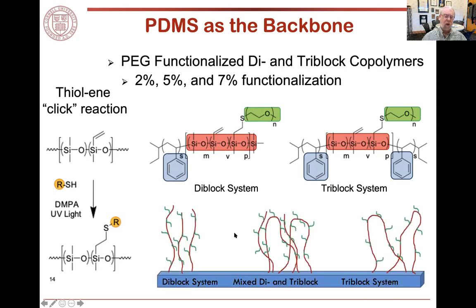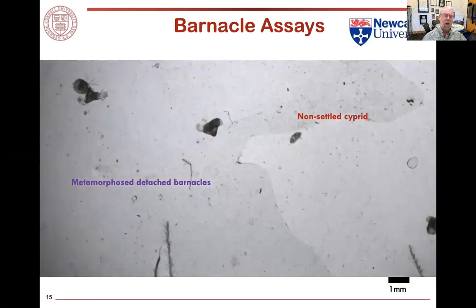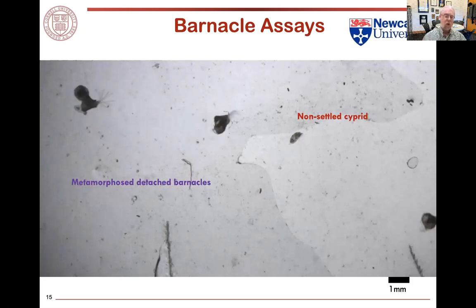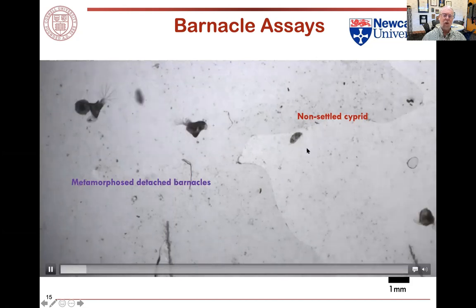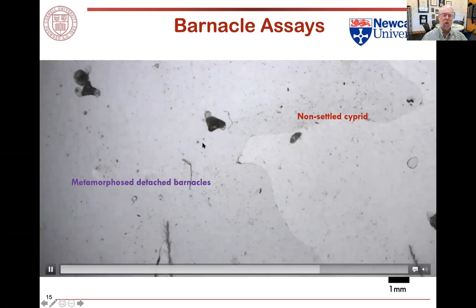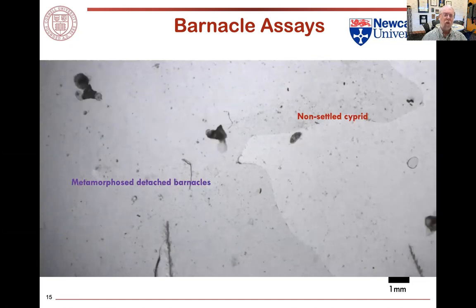We can also use diblocks or triblocks or mixed structures to modify the surface. And we've done that, and you see, I hope, in this short video clip, a series of barnacles, in this case a barnacle cyprid, lying on the surface, trying to figure out what it's doing there. Barnacles have generally a conical shape, kind of like a volcano. The reason they're swimming around is that their feeding flagella are causing them to move because they are not attached. This particular coating is very, very good at resisting fouling.